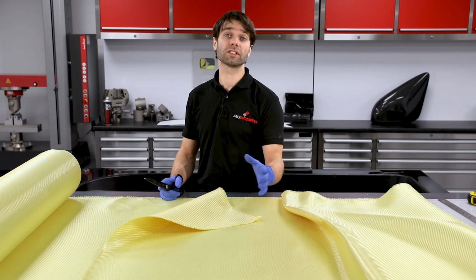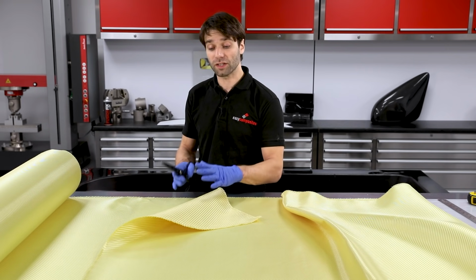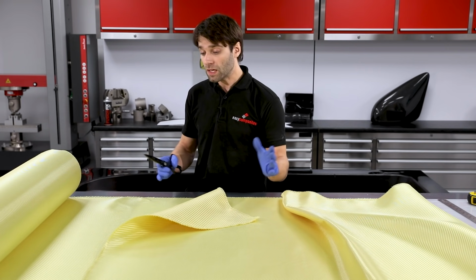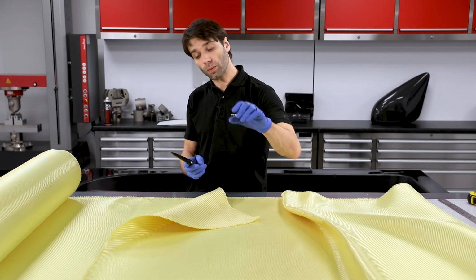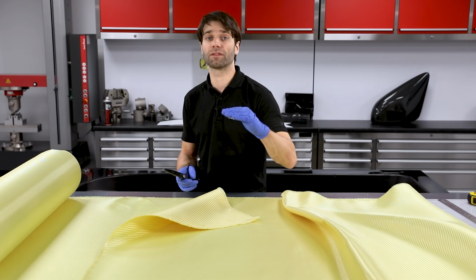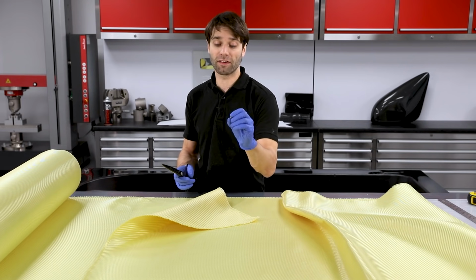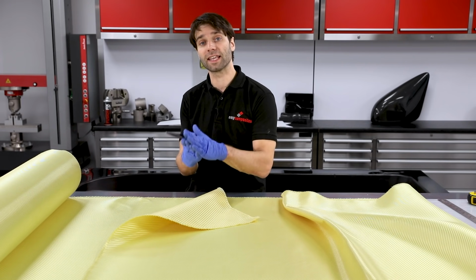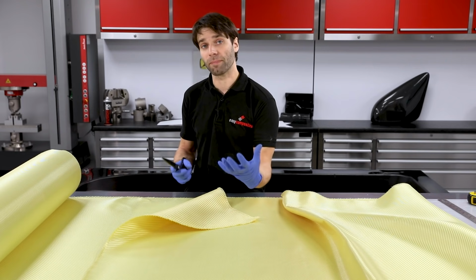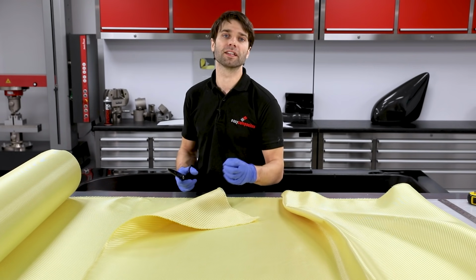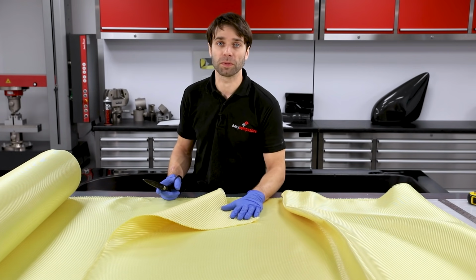If you did watch our material selection video, you'll know that we decided to use Kevlar for the build of this sledge. So in the areas where we have the core, we're going to be running 2 plies either side of the core. And then in the solid laminate areas, we're going to put an additional 3 plies there to give it reinforcement in the high impact areas, and then 1 or 2 areas where there'll be even more localized reinforcement.